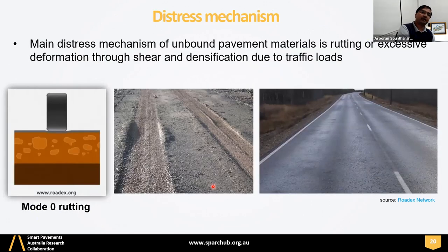Right. Let's look at the distress mechanisms commonly identified in unbound granular materials or unbound pavements. As I mentioned earlier, the predominant failure mechanism is rutting, right? And how does rutting occur? Because unbound granular material hasn't got any tensile strength, because you don't have cement or cementitious binders in it. So predominantly it fails through shear as well as densification. Densification happens due to the traffic. So it's more like rutting.